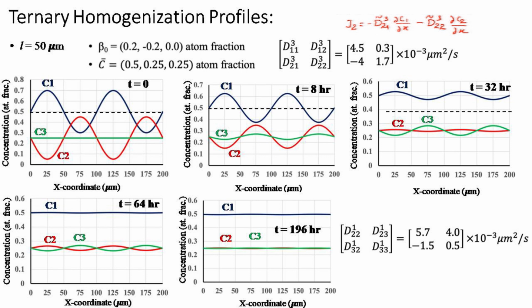So, both the gradients are higher, and C1 is flattening out very fast. So, the interaction effect of 1 and 2 is not very obvious here. And by the time C1 has flattened out, the gradient in C3 has picked up, and so the interaction of 3 on 2 has come into effect.